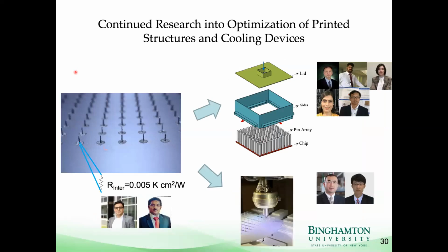So just to summarize this printing onto silicon project so far, we've shown that we could print fins onto silicon, and that these can have lower resistances than conventional metal TIMs, even those that are kind of the best performance on the market now. We also have been looking at how to optimize the cooling geometry and topology of heat sinks, as well as looking at the mechanical properties, so we can actually use this in a real device.